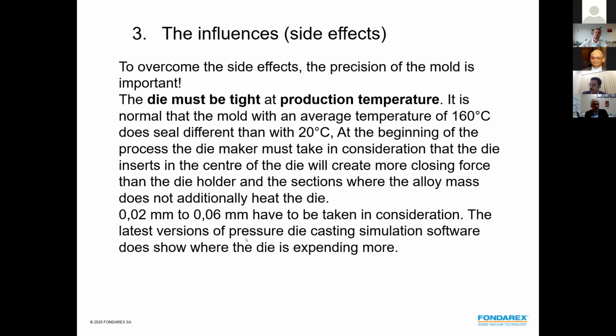And I think this is the biggest challenge for every die maker. It does need some experience. The die maker has to work well together with the die caster. And of course, the latest simulation systems are sometimes able to show where we would have a higher expansion of inserts or of the whole die because of temperature. But still at the very end, we need to imagine a little bit something which gets hot, extends, and we have to take this into consideration once the die is made to be very successful for vacuum pressure die casting.